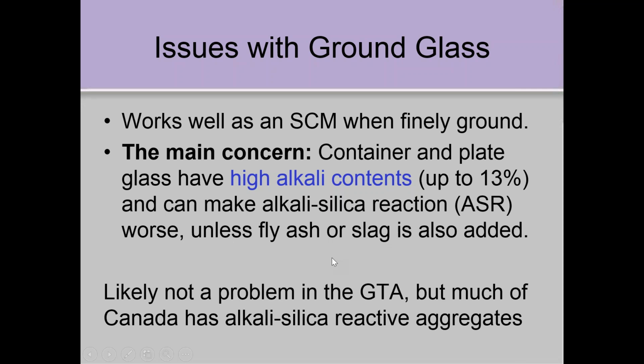And that sort of work's ongoing, and I think that's what we're looking at before we adopt it in the concrete standard. Now, ASR is not a big deal in the Greater Toronto area, but much of Ontario has alkali silica reactive aggregates, so it would be a concern.